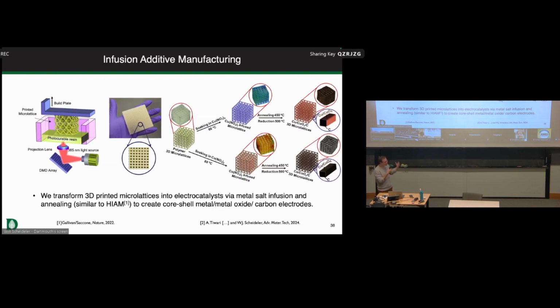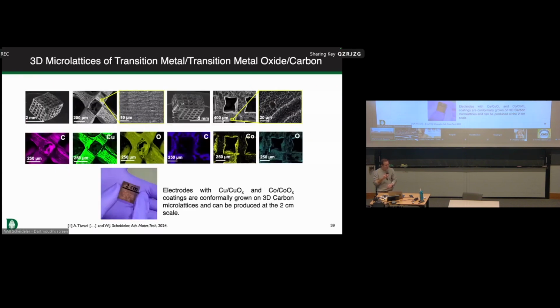So what we discovered is that this structure, well, the first feature that we care about is that it can have some essentially mesoscale structure. It can have some pores that could give us the electrolyte diffusion and the bubble evolution, but it also gives us some means of controlling the nanoscale structure at the surface. So for most electrochemical devices, we want high surface area. We can get that in two ways.